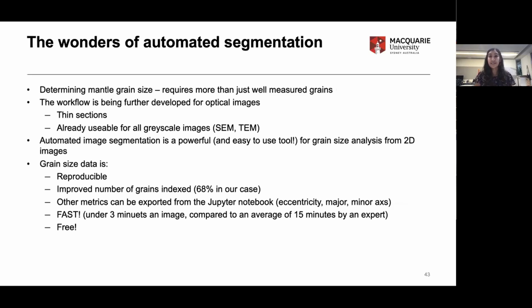The grain size that we've been able to get out from our workflow is reproducible. We've improved the number of grains indexed, 68% in our case, and other metrics can be exported from the Jupyter Notebook. These include eccentricity, major and minor axis. And the best part, it's really, really fast, under 3 minutes an image, compared to the average 15 minutes it took me. And the best bit, as science should be, it's completely free and everyone's welcome to use it.